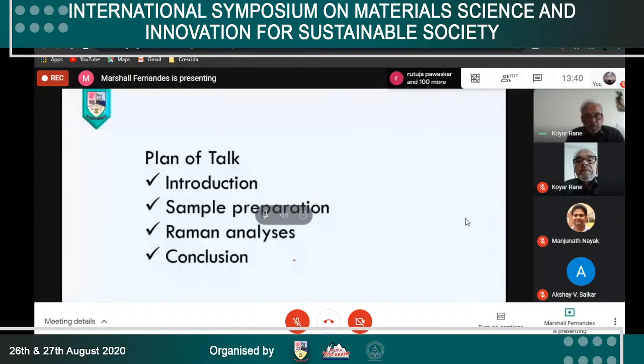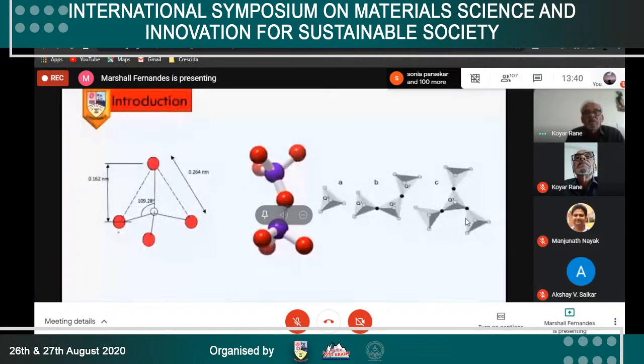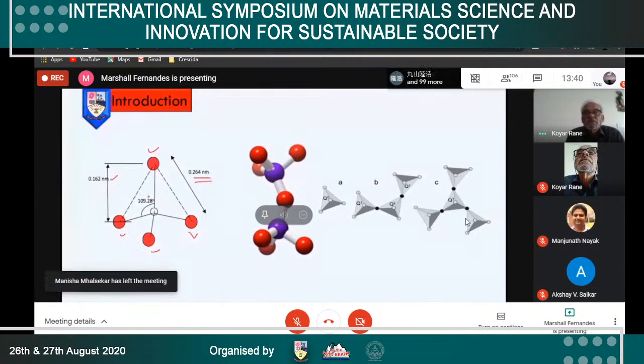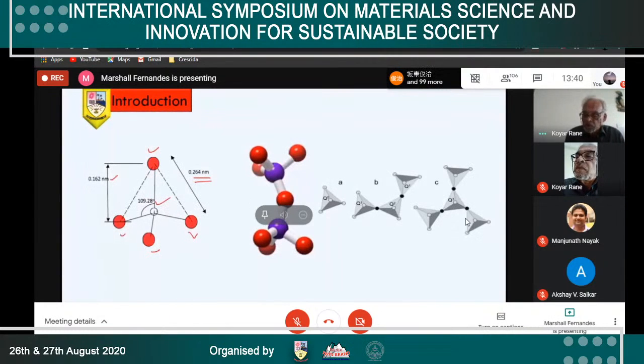So let me begin. The sample under study is a glass material. As you know, they are amorphous in nature, that is, they possess no regular long-range periodic arrangement. However, at a short range, the local structure of each unit is highly ordered. The glasses presented here for today's talk are the silicate glasses, and the local structure of each silicate is of a tetrahedral nature, with each silicon atom surrounded by 4 oxygen atoms as shown here. With a Si-O distance of 1.62 angstroms or 0.162 nanometers, an O-O distance of 2.64 angstroms, and a tetrahedral angle of O-Si-O of 109.28 degrees.